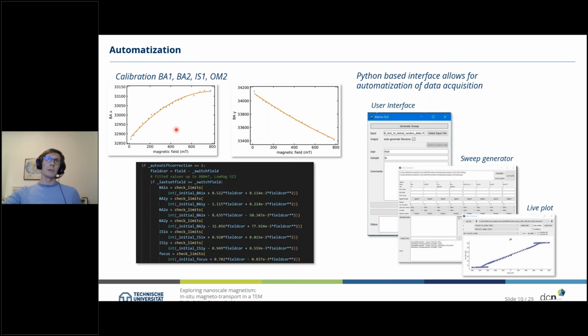And if you do so, we ended up with functions for the different shifts and tilts and defoci. We saw that this can be nicely described by polynomials up to second order, so either linear or quadratic, with different coefficients as a function of the magnetic field. Having these calibration curves, using a Python code we can then apply any magnetic field and directly compensate shifts and tilts and defocus of our lens system to have stable imaging conditions for our different field sweeps, for example. All that is integrated into a Python-based user interface where you can put in sample name and so on,